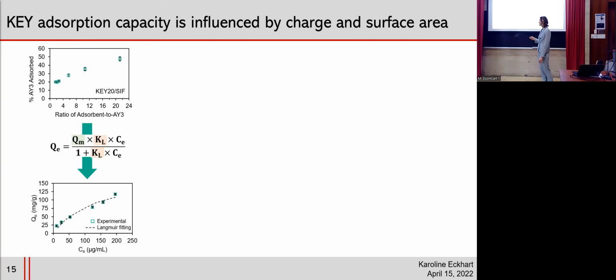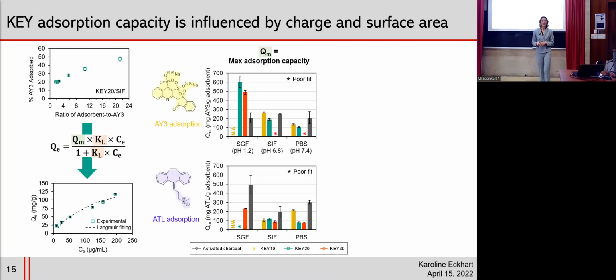And we fit this experimental data to the Langmuir isotherm model. The equation is shown here. And the goal here is by inputting the QE and the CE values, which we know experimentally, we can back calculate QM and KL. QM is the maximum adsorption capacity of the system.